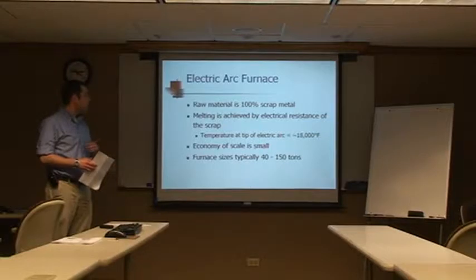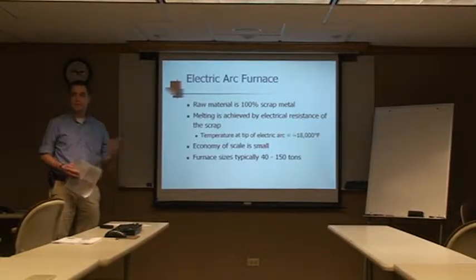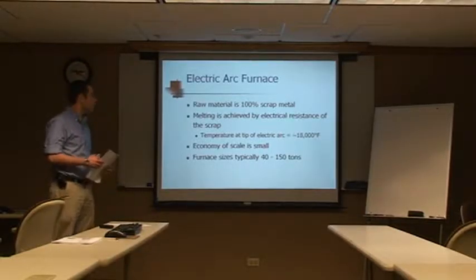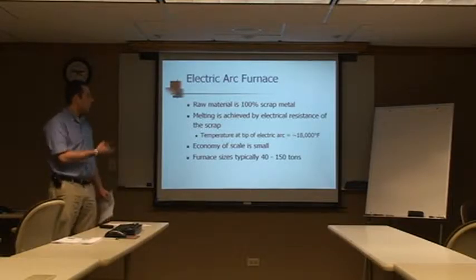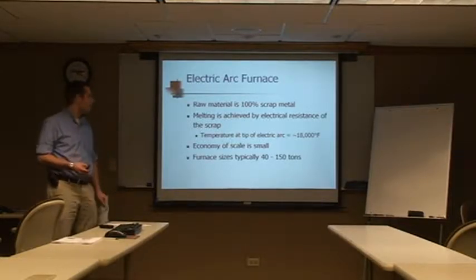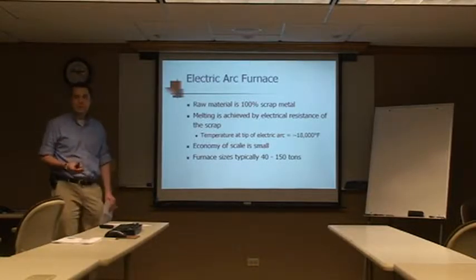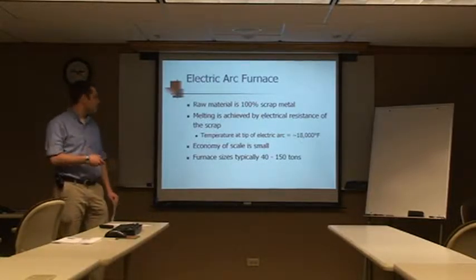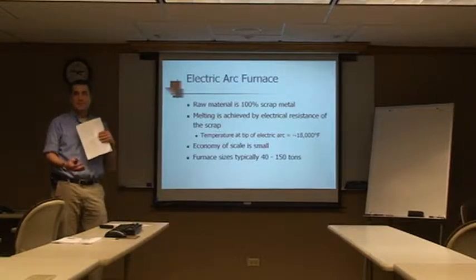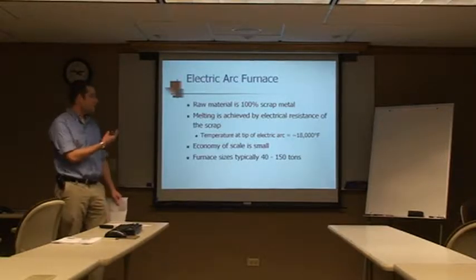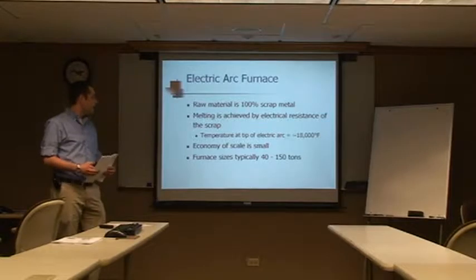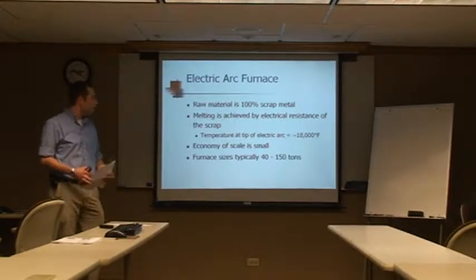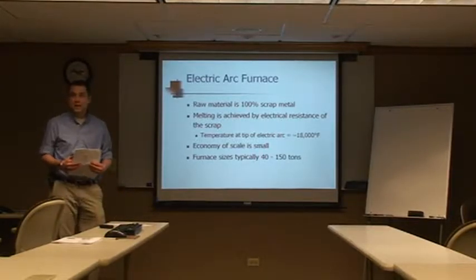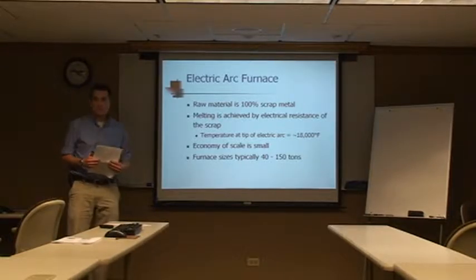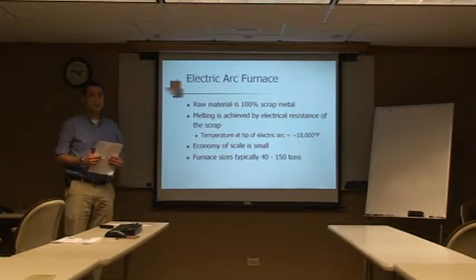First thing I'm going to start out with is the electric arc furnace, because that's where steelmaking starts for us. We use 100% scrap material, recycle it, and we melt the scrap material using electrical resistance to the scrap, which creates an electric arc, which is the namesake of the electric arc furnace. And as I've shown here, the temperature at the tip of the arc is about 18,000 degrees Fahrenheit. 18,000 degrees Fahrenheit is extremely hot.